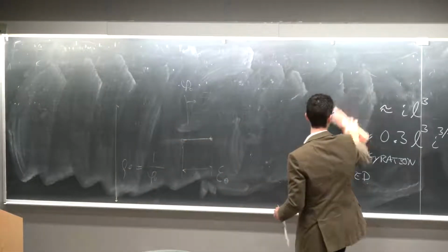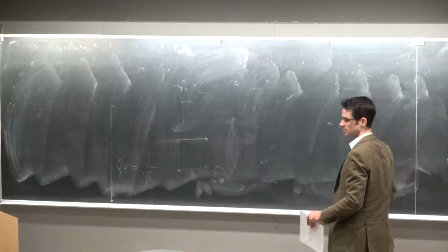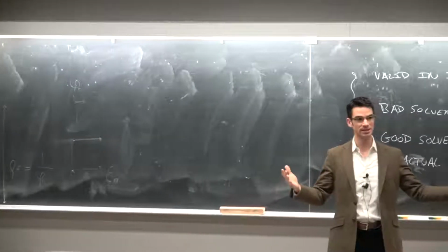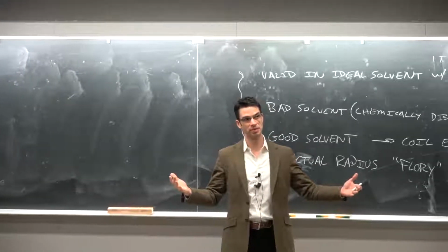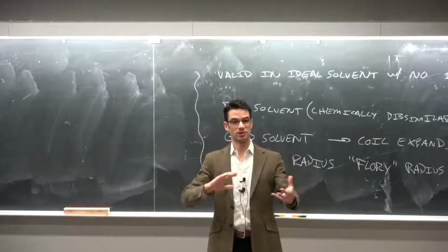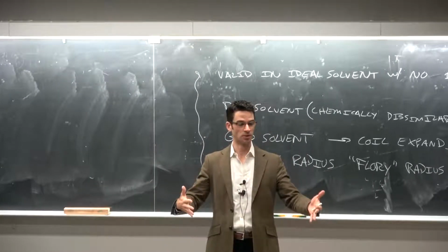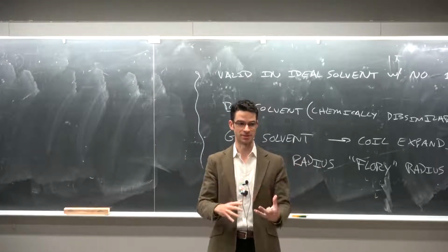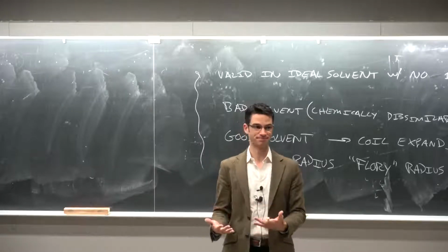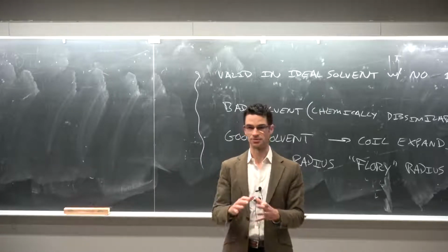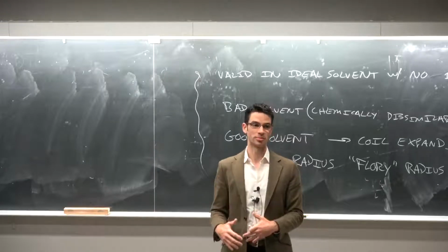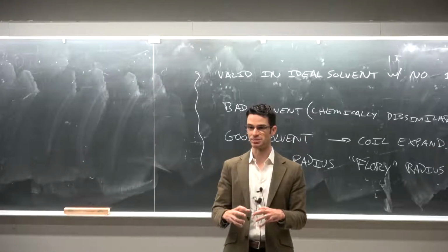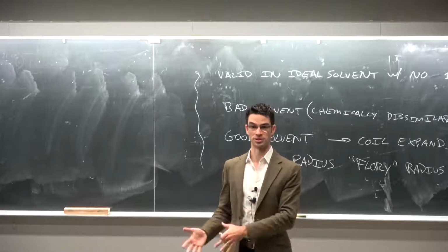of a polymer solution upon either crystallization, so you either take the melt and you cool it down. There are two ways of making a solid polymer. Maybe three ways. You take the polymer in solution and you cast a film, or you pour it into a mold or something, and then you allow the solvent to evaporate, and then the film solidifies. You could also take a polymer and melt it. It'd be a thermoplastic, and then it forms in a new shape. Or it could be a thermoset polymer, which is a polymer that undergoes a chemical reaction to become a solid material from a liquid precursor.